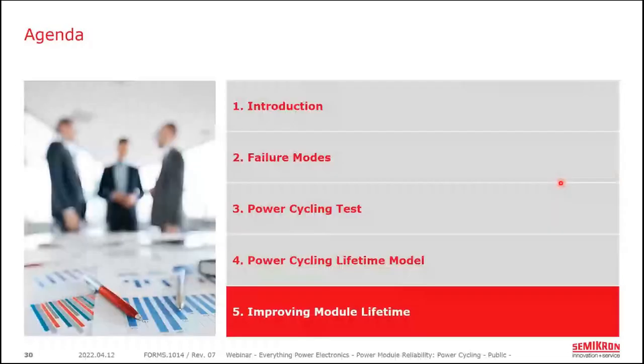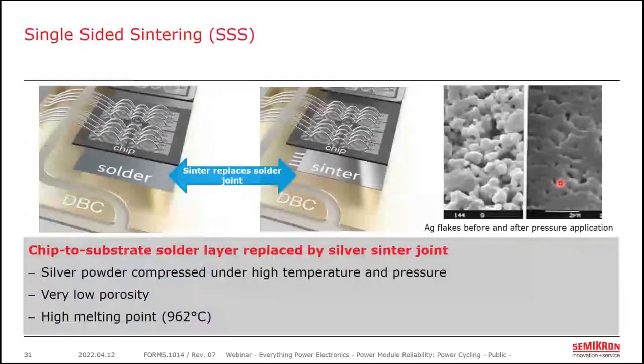Now, lastly, let's talk a little bit about what we can do to improve the power cycling capability of modules. So I'll show you some technologies that Semikron has developed to improve that power cycling capability. Since we know that solder is one of the weak points in terms of degradation to the thermal stress, one of the obvious things we can do is replace that solder with something that's more robust. So notably a layer of sintered silver.